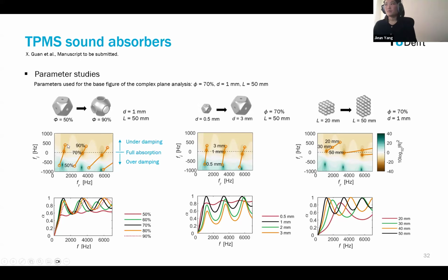of this reflection coefficient if you draw them in this complex frequency plane. And then if the zeros of the reflection coefficient coincide on this real axis of the frequency, then they have full absorption. And if the zeros are located above this real axis, then you have underdamping, and below is overdamping. So then you get a little bit farther away from the full absorption. And then that can be seen in this sound absorption graph.